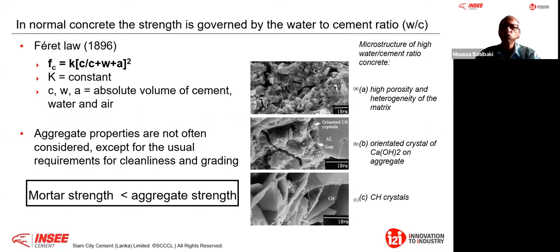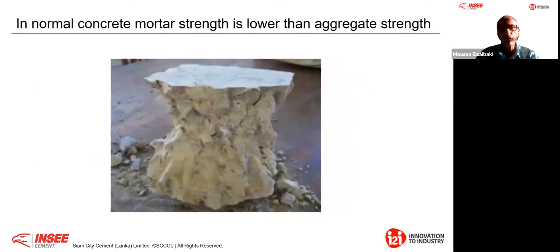In normal concrete, if you look at the microstructure, you see that you have high porosity and heterogeneity of the matrix. You have oriented crystals of Portlandite on the aggregate. You see how this Portlandite is oriented at the interface with the aggregate, which gives you weakness in flexural strength, E modulus, compressive strength, and fatigue. With different cycles of fatigue, you can develop internal cracks. And at the same time, you will see that this mortar strength very often is lower than the aggregate strength. When you break a cube, very often you don't break the aggregate. It goes through the cement hydrated paste.